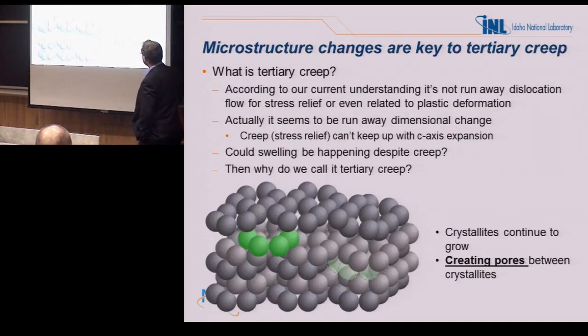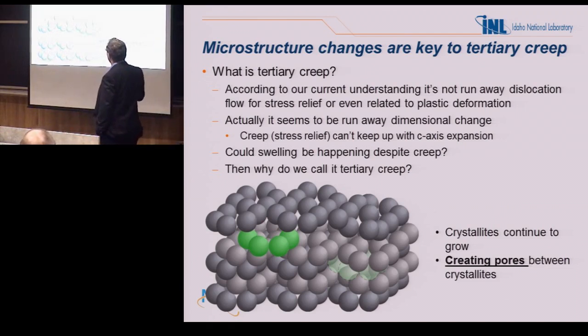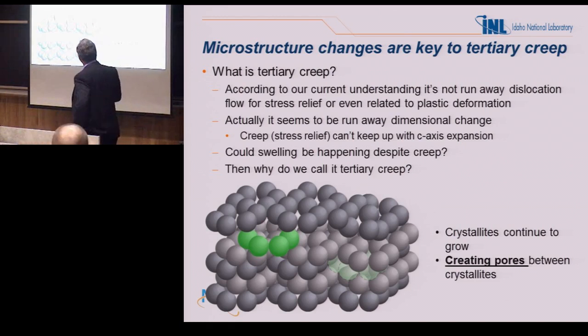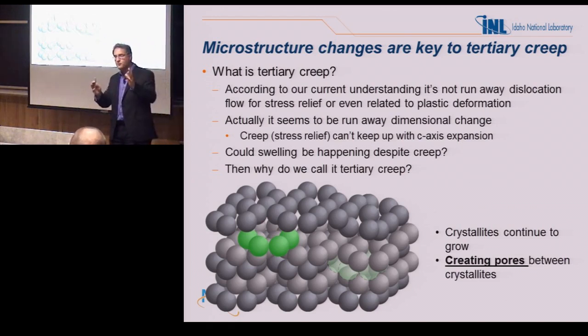Okay. So the microstructure changes are key to the tertiary creep. Again, what is tertiary creep? According to our current understanding, it's not runaway dislocation flow. Otherwise, it would just relax and these things would turn into silly putty over time. All right? It doesn't happen. What we think is actually happening seems to be runaway dimensional change. Creep keeps up with it for a while and then finally it just pukes out.